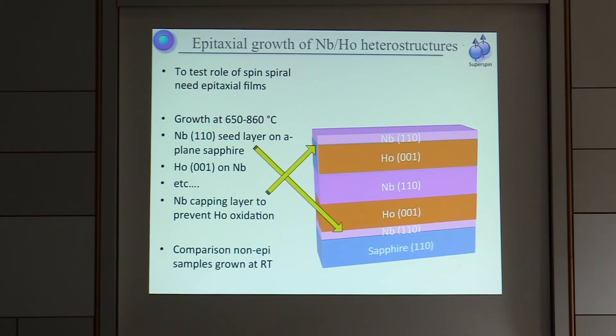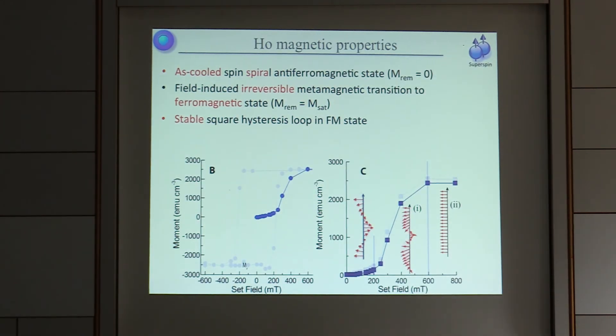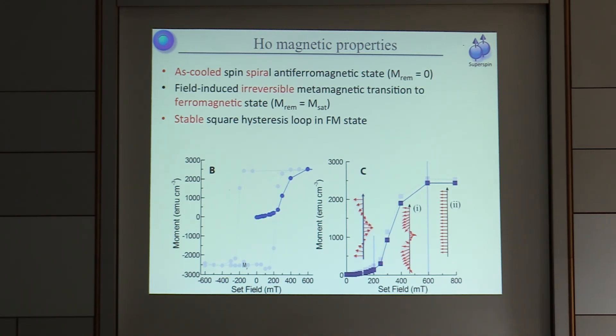These are epitaxial systems. This is holmium, which has been discussed in many previous talks as having spiral magnetism — but you can turn that off if it's an epitaxial system. The magnetization curve of an epitaxial holmium film as-grown does have this spiral structure, giving zero net moment, but if you apply a large field of about half a tesla you switch it irreversibly into a ferromagnetic state. You then get a square hysteresis loop with large remanence and quite a large coercivity.